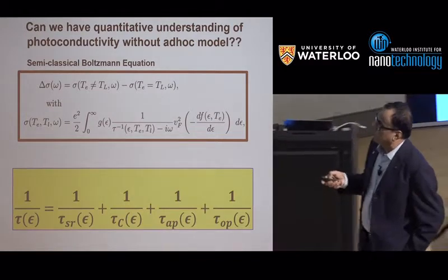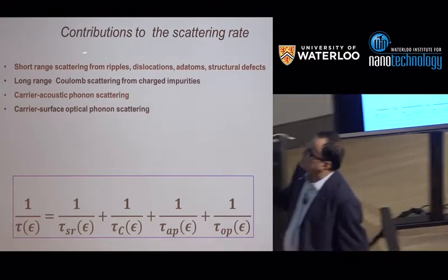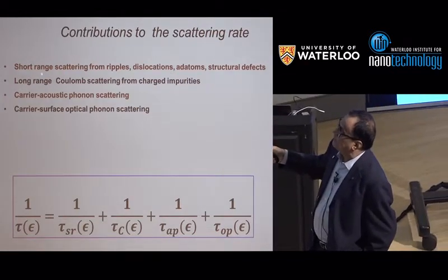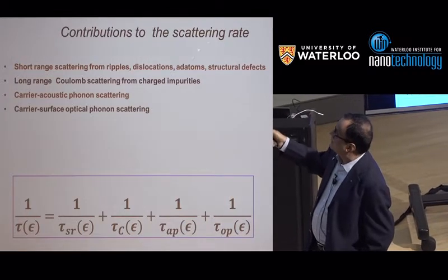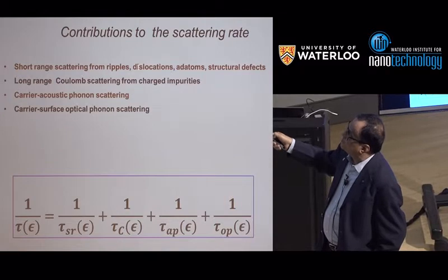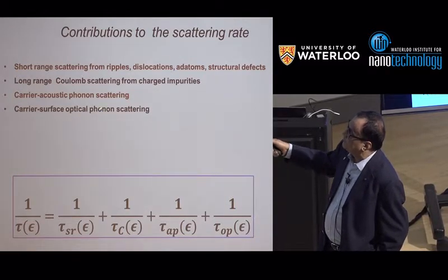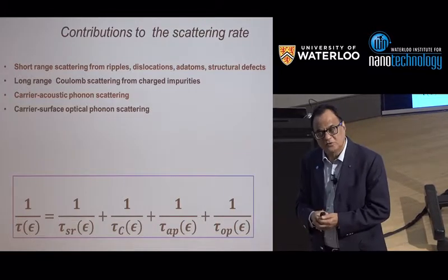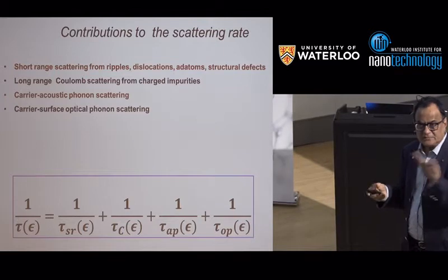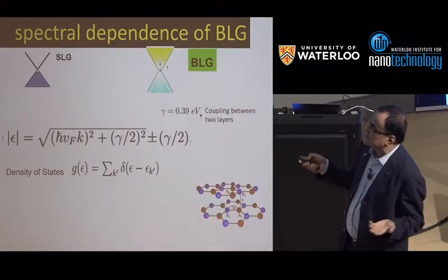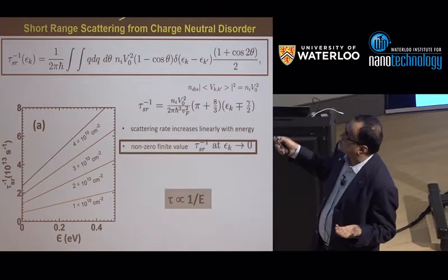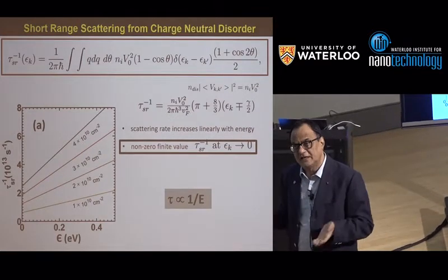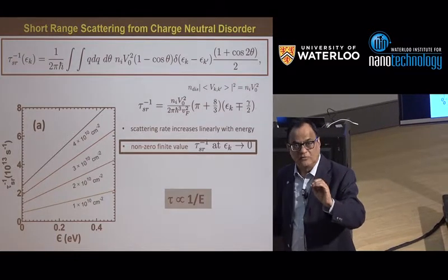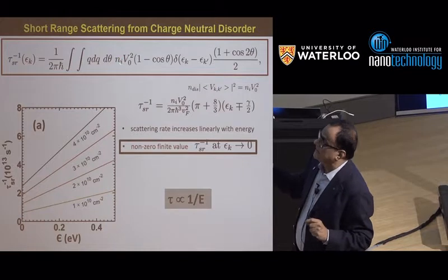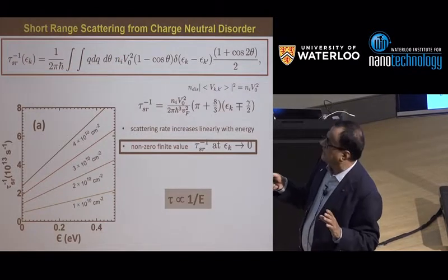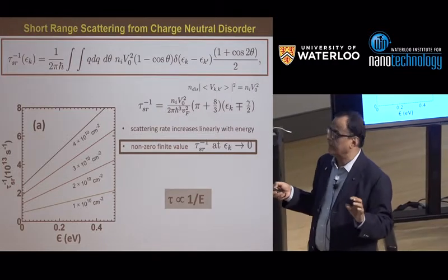This is the project which took us 2 years, where we considered various contributions like scattering of electrons from ripples, dislocations, adatom and structural defects, long range Coulomb interaction from charged impurities, carrier scattering from acoustic phonons, carrier scattering from surface optical phonons. All this we did, and I will not give you the details because they are all in the paper. We know the density of states of bilayer. We put for each process the microscopic, quantum mechanical expression, and the only things unknown for us are the interaction potential and their density, the two things which we take as experimental adjustable parameters, with a caveat.